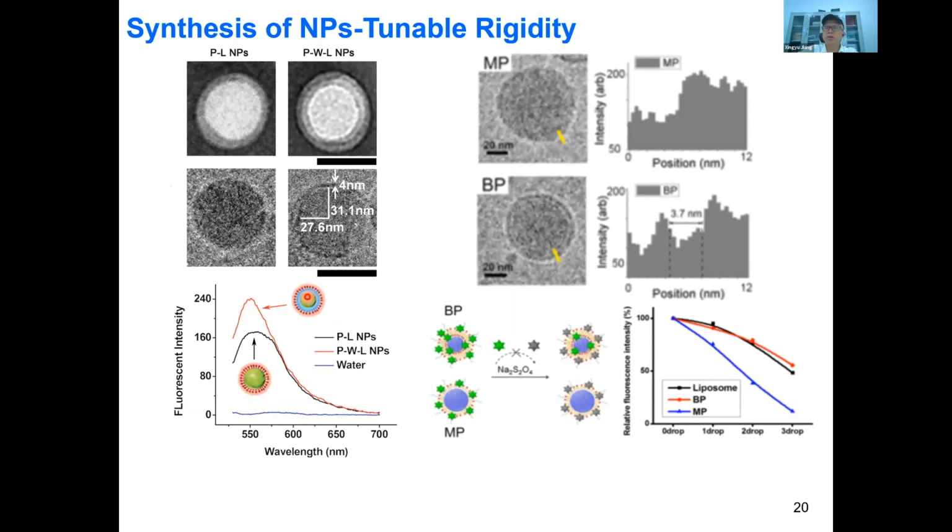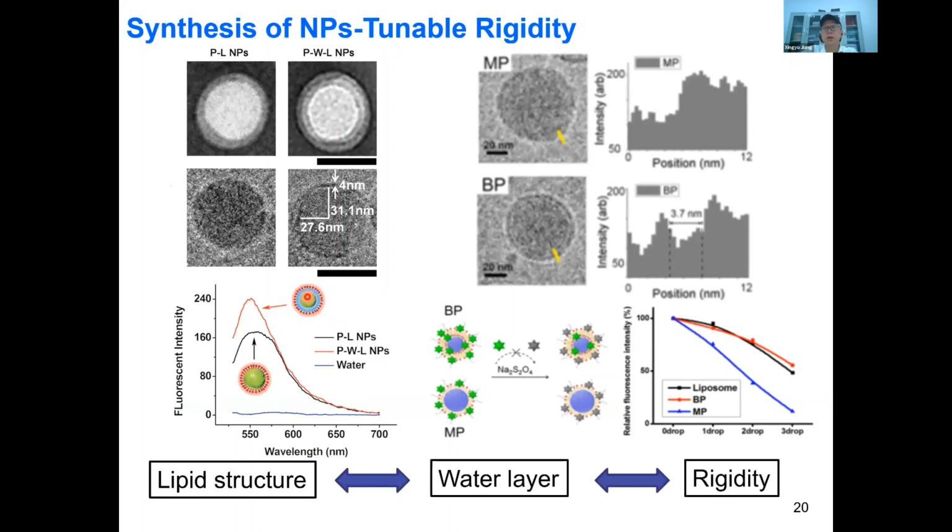And we also use atomic force microscopy to test, and indeed the ones that do have water are much softer than the ones that don't. So you can think about the ones that do have water as a water-filled balloon that's easily deformed if you squish it. But here, it's just the skin of the balloon directly covering a piece of rock. So it's hard.